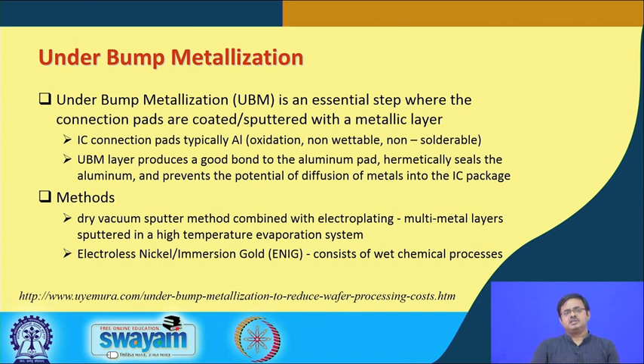Okay. The other one which has become more common these days, even though it is not the most popular yet, is called electroless nickel immersion gold, ENIG. Dry vacuum sputter is still the most commonly used, but this is also becoming popular. This is a different process, it is an electroless plating, and it consists of wet chemical processes. We are not getting into details of these, but if you want more information about these various methods, the drawbacks, the difference between UBM of aluminum and copper, then the link that I have given at the bottom of the slide is quite informative. If you go there, you will find a lot more information on under bump metallization.